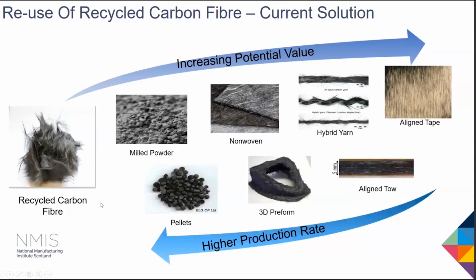So lots of engineers and researchers are currently working on developing a reprocessing process to convert this fluffy and 3D randomized recycled fiber to several intermediate products. If you're working in the composite manufacturing area, you may be familiar with the milled powders and the pellets. They are very easy to manufacture by low-cost processes, but the product value becomes very low, and although they have been widely used, the market has been fully filled. Currently, the non-wovens and the 3D preform are becoming very popular, but due to the random fiber orientation, you can't achieve very high mechanical properties, and maybe you can increase to a very high molding pressure, but it will lead to fiber breakage.